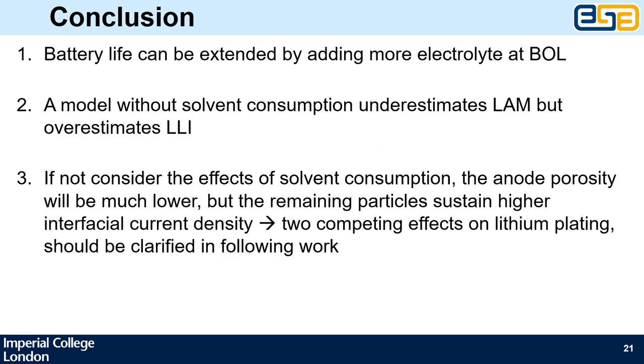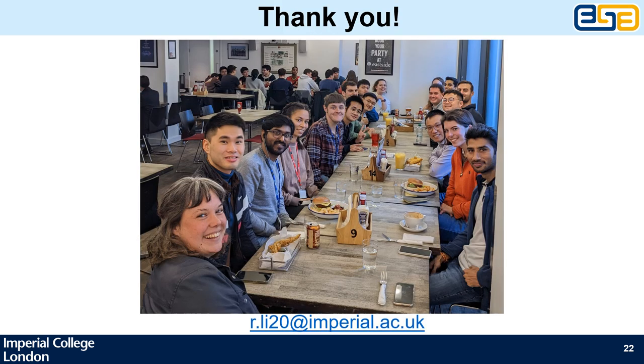To draw conclusions and give a summary: the extra electrolyte inside the cell is not just there to keep the cell wet — the amount of solvent is very important and will affect how long your battery can last. But if you have too much extra electrolyte, you lose energy density. A technique that allows injection of electrolyte into cells after a period of usage may be an easy way to prolong battery life. If you don't consider this solvent consumption model, you will underestimate loss of active material but overestimate loss of lithium inventory, which may be problematic when more complicated aging mechanisms are involved. Finally, we notice two possible competing effects in our model that may relate to lithium plating, which we are currently working on. I want to express my deepest gratitude to my group members, especially my supervisors Greg, Monica, and Simon. Thank you very much.